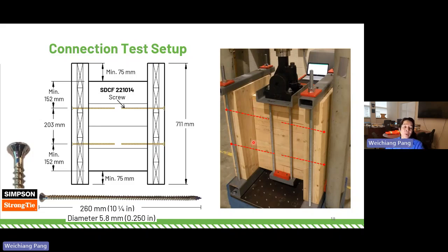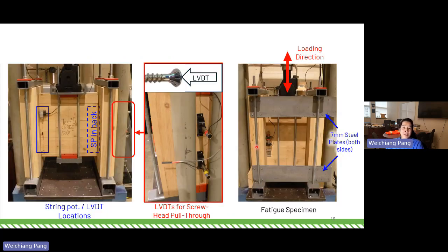This drawing here shows one of the tests we performed using the Simpson Strong-Tie screw. We also tested the Rothoblaas screw and sharp metal in this setup. So this is what the test looked like. We put LVDTs to monitor the screw head pull-in during the test. We noticed during the test that the screw head actually gets pulled into the CLT panel. We also have string pots to measure the slip between the CLT panel and the glulam beam.